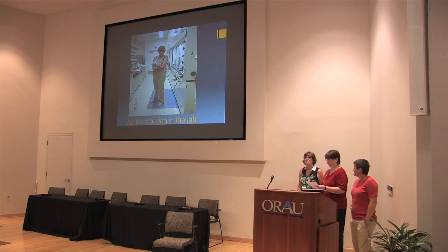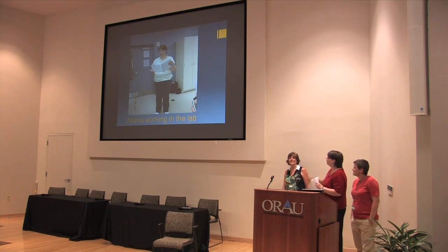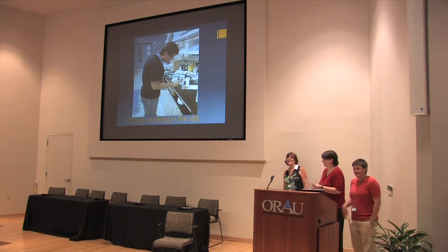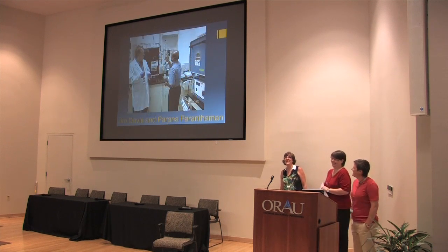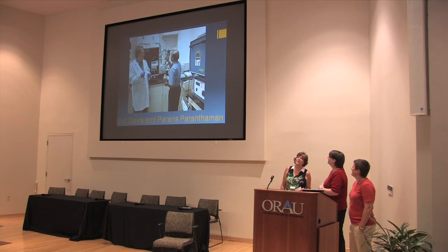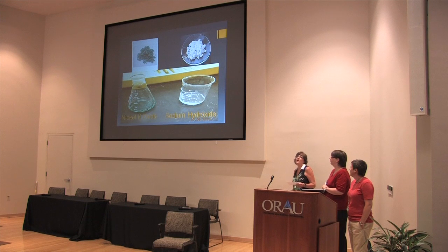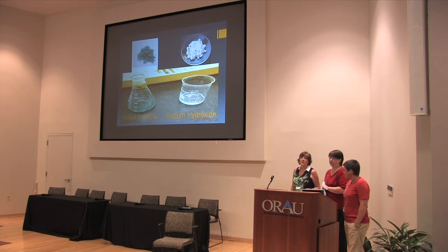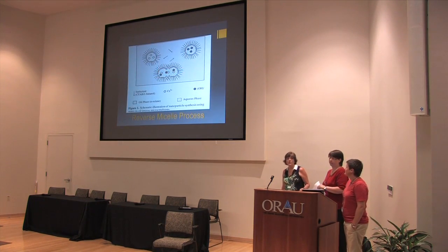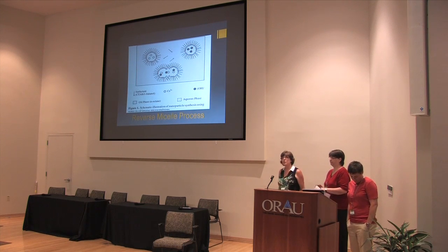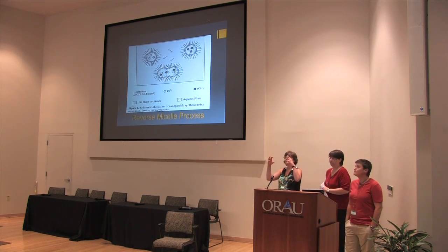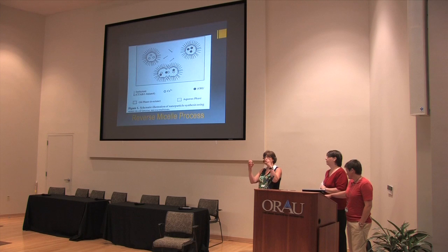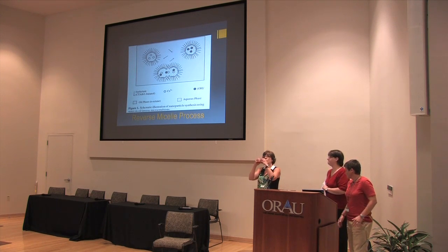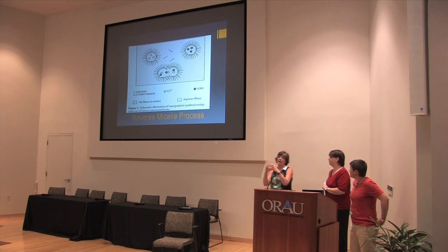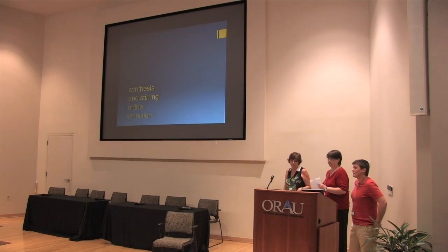It's me working in the lab. Me working in the lab. And me in the lab. These are our two mentors, and what we did is basically made a surface for anode half cells. We made nickel hydroxide, and what was different is we used the reverse micelle process, where you take two micelles and put the two reactants inside each one, so that when they come together, you have a mini reaction. And that mini reaction forms small nanoparticles.